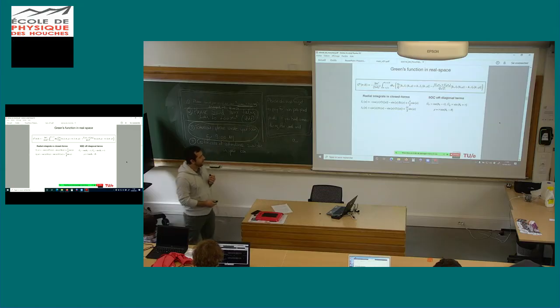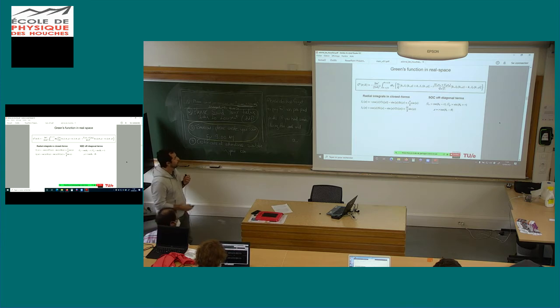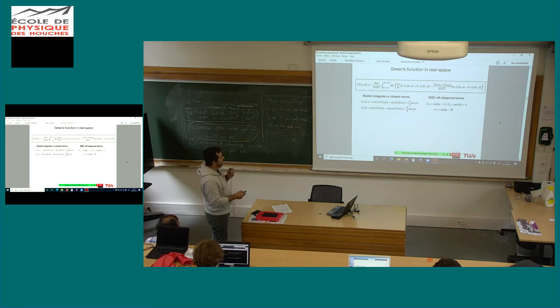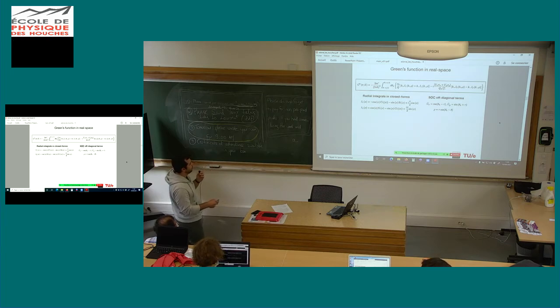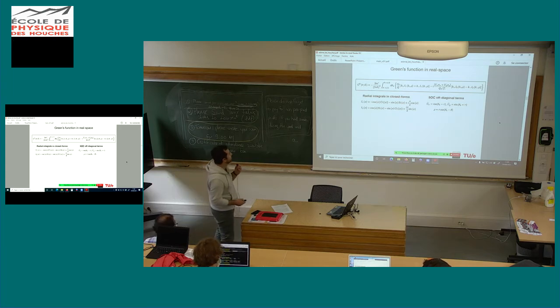Based on that simple Hamiltonian, what we did was to describe the Green's function in real space, basically evaluating the resolvent in k space. For general alpha and beta, we cannot have a fully analytical expression, because we still have this angular integral in k space, although the radial integrals we can basically solve in terms of trigonometric integrals. This problem is exactly analytical when just alpha is present in the system, and we can write it in terms of Hankel functions.